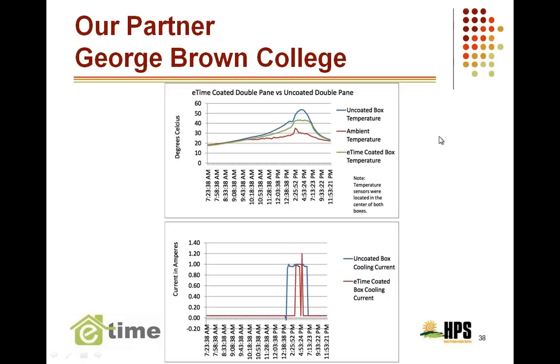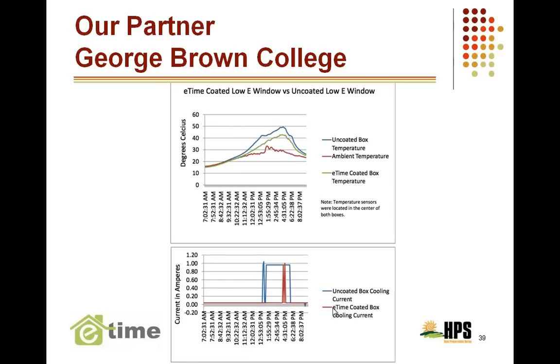The interesting thing is at the bottom, you'll see a spike that comes up in red or in blue. The blue is the uncoated box and the current being drawn in order to activate the cooling. You'll see it's almost 2 to 1 in relation to the coated box versus the uncoated box. And that's dramatic. It's reducing your cost by almost 50% because you did not have to have the cooling load on. If you look at the next page, this is low E windows, and we wanted to find out whether or not it affected different types of fenestration.